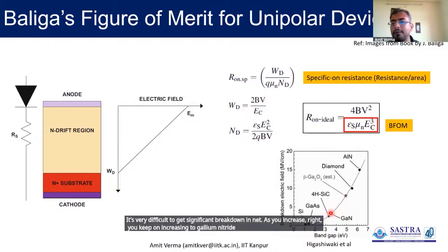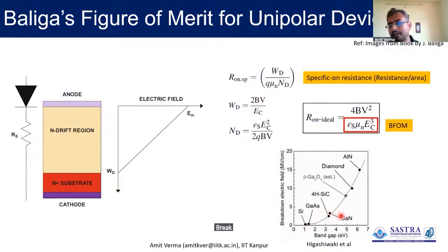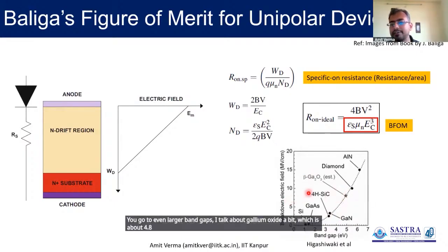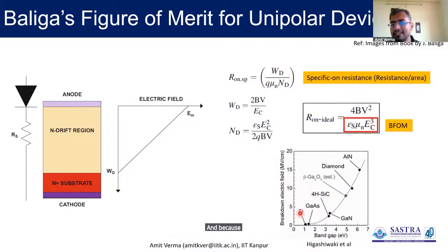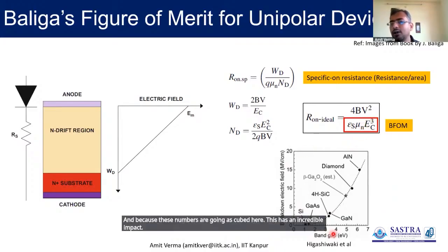This is one of the very popular materials. Band gap is about 3.4 eV. Breakdown fields are about 4 megavolts per centimeter or so. You go to even larger band gaps. I'll talk about gallium oxide a bit, which is about 4.8 eV. The breakdown fields are about 7 to 8 megavolts per centimeter. And because these numbers go as a cube here, this has an incredible impact on this trade-off.